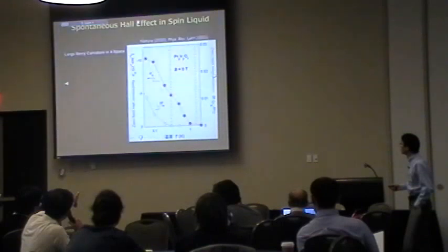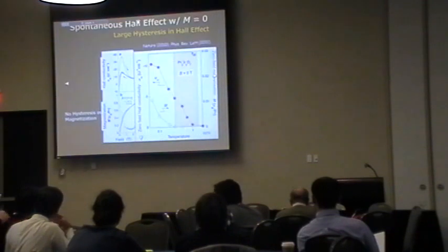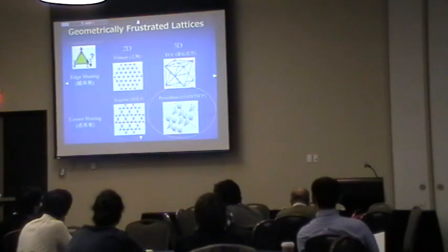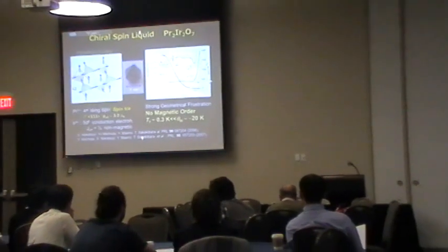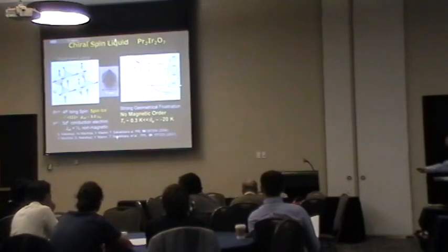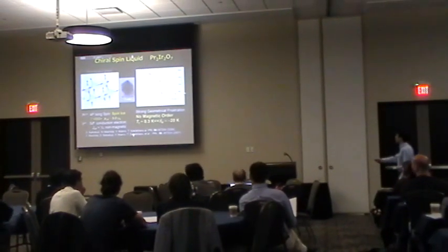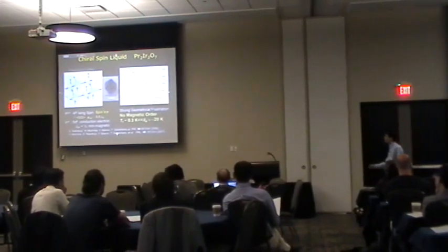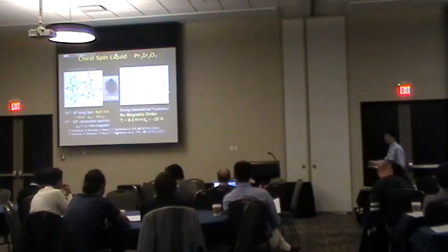This one. Okay. So you have this zero field magnetization, uniform magnetization. Where is this coming from? If you make your magnet perfect, this is very tiny. This is field cooled, and there is a field susceptibility. We believe this comes from the imperfection of the particle: some of the spins cannot find their neighbors, so they are left alone and cannot form the triangular state. That may induce this type of small hysteresis.